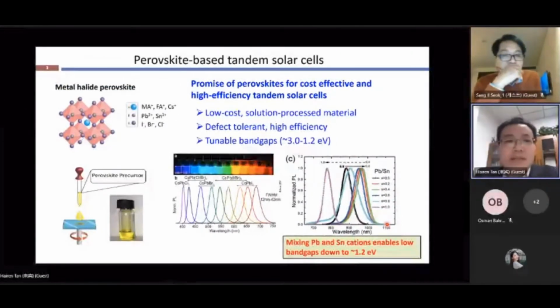Professor Osman Bakr has introduced the excellent properties of perovskite materials, and in addition to his introduction, I think perovskite material is very promising for low-cost and high-efficiency tandem devices, especially because we can easily tune the band gaps of these halide perovskite materials by changing the composition, especially the halide composition at the X site and also the metal cations at the B site. For example, if we mix the lead and tin at the B site, we can even lower the band gap of the perovskite down to 1.2 eV.